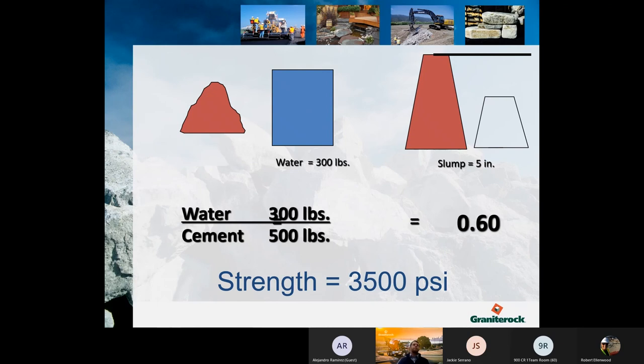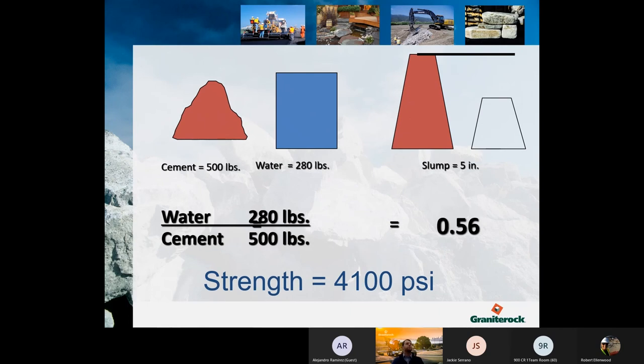So to give an example of how water reducers work, one, they make the concrete wetter, which is easier to place, but the secondary effect is also increasing the strength. To get a visual of this, this would be a normal mix, so a 0.60 water cement ratio, call it 300 pounds of water to 500 pounds of cement per yard to achieve about a 5-inch slump. Now, if we add a water reducer, we can take out 20 pounds of water, keep the same amount of cement and the same slump. So you're affecting your water cement ratio, decreasing to a 0.56, which increases your strength about 5 to 600 PSI. So good benefits here using a water reducer.